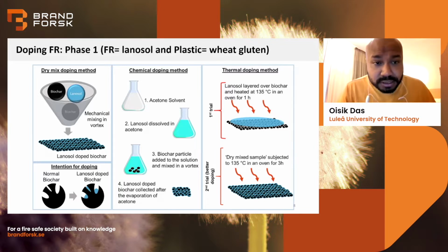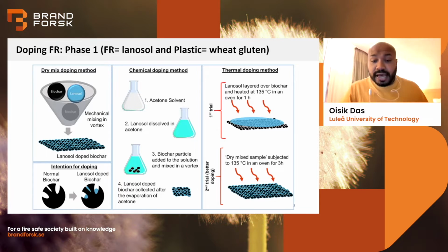The first was dry mix. So basically we mix the biochar and the fire retardant particles together. The second was chemical doping, where we dissolved the fire retardant in acetone, and then we added the biochar to that solution and let the acetone evaporate. And the third method was to melt the fire retardant at 135 degrees centigrade over the biochar for 1 hour and also for 3 hours.